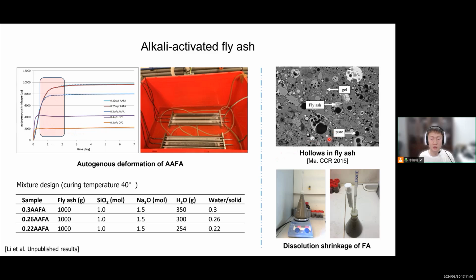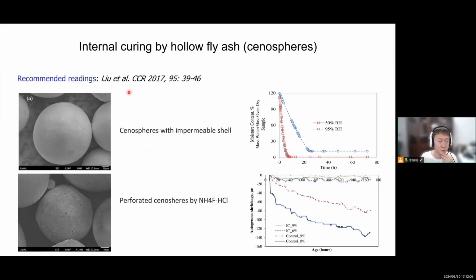If I'm allowed to say a bit more about this, I'm also thinking that this kind of spheres or hollow spheres can be used for internal curing. For example, if we pre-store some liquid inside, then at later age during the dissolution, after exposure, the liquid can join the reaction and compensate the self-desiccation. But then I found someone already studied this, for example, by Liu. So he used some acid to pre-dissolve the flash. You can see some holes there, and then some solution is sucked inside, and then after mixing and in the hardened paste, this kind of spheres have the potential to provide internal curing. Because this expert has studied this, I didn't go into detail, so just recommended readings here.